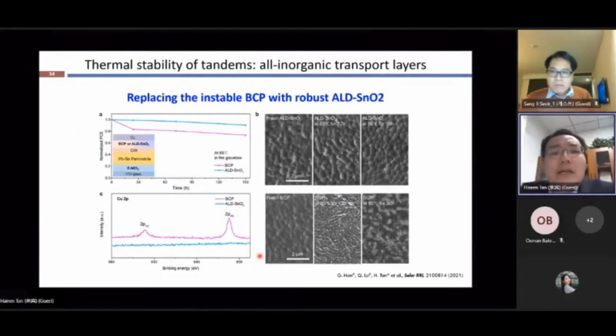Another point to improve the thermal stability is that we have to remove this BCP in the inverted perovskite devices, and we can do this with metal oxide. We found that the BCP layer is not thermally stable because it will aggregate after thermal stressing at 85 degrees. And by using this metal oxide layer, we get another benefit: we can prevent the diffusion of the metal electrodes into the perovskite film, as we can see from the XPS spectra.